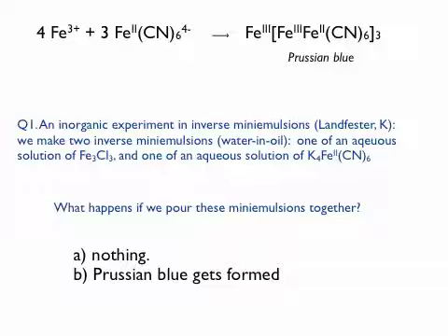The only way reactant A and reactant B could react is if A diffuses through the continuous phase into B, or B into A, or if the two droplets merge. If the droplets are colloidally stable, if I use the right surfactant, they wouldn't bump into each other. It's a colloidally stable system.